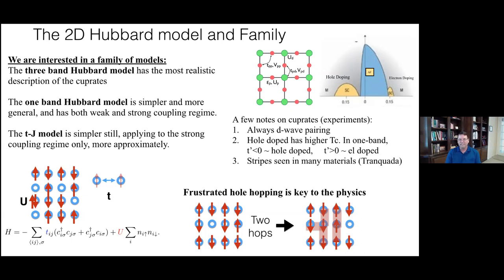A key to the physics is that the hole hopping in the antiferromagnetic background is frustrated. So the system wants to have antiferromagnetism, but also the holes moving around freely to have low kinetic energy. And if a hole in this lower picture hops two sites to the right, then it essentially trades places with the spins, and it makes a line of bonds which are parallel. So the antiferromagnetism is messed up. The red wide bonds are messed up antiferromagnetism because the hole has hopped two sites to the right. So that's a simple strong-coupling picture of what's going on. That's a nice simple picture.